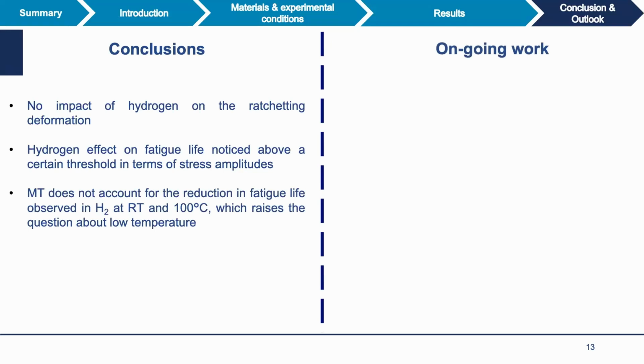So this is a brief summary of what I've shown today. We have no impact of hydrogen on the ratcheting and deformation. We noticed the hydrogen effect on fatigue life above a threshold in terms of stress amplitude. And it seems that martensitic transformation cannot account for the reduction in fatigue life, at least at room temperature and 100 degrees C. So we are still working on that.